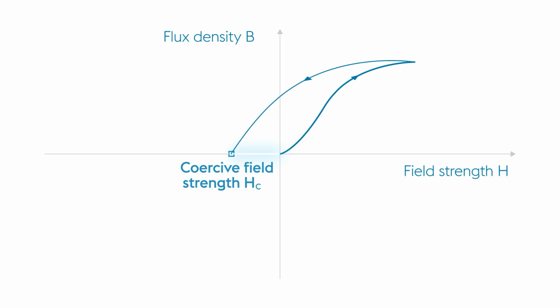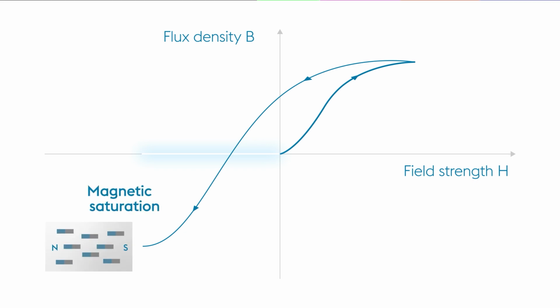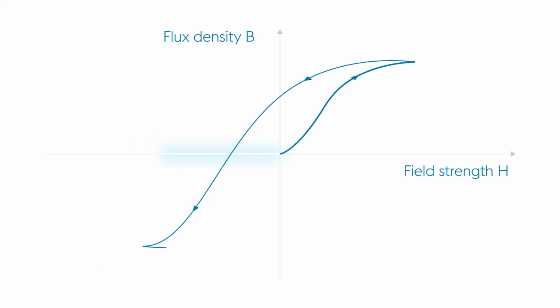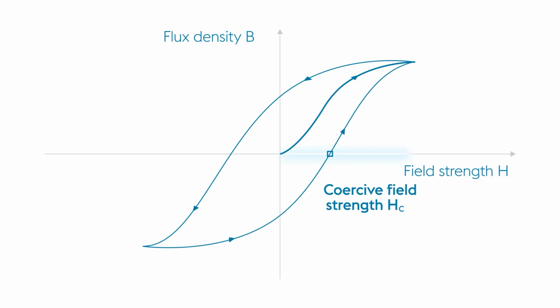If I further increase the current, and thus the field strength, all the dipoles will align again at a certain point, and the material will again reach a point of magnetic saturation. But now the electrical steel is fully magnetized in the other direction. Reduce the current to zero, to remanence, then current in the other direction to coercive field strength, and then continue to saturation. The dipoles are always aligned along the outer loop and always follow the change in the direction of the current.